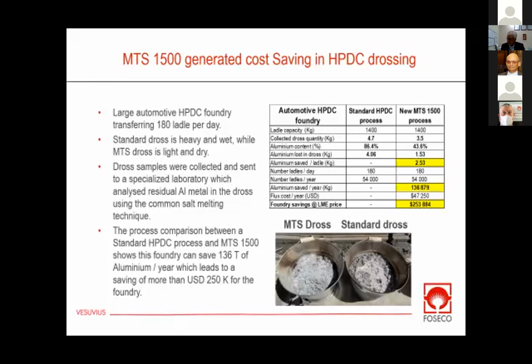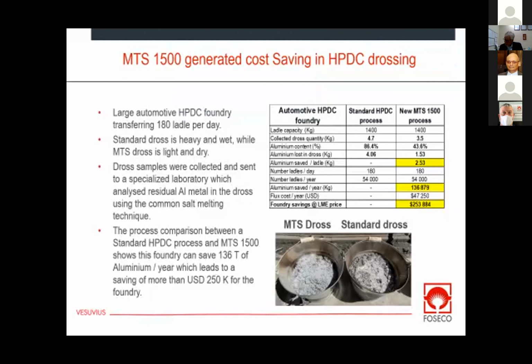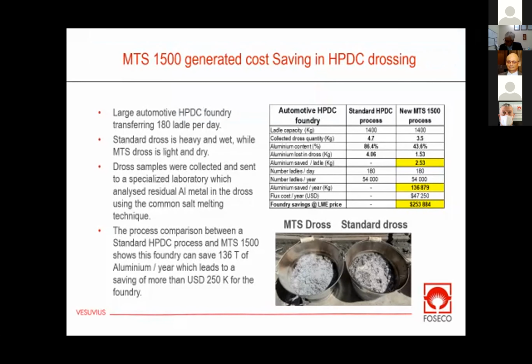We looked at their standard process, and quality-wise, they were very happy. They didn't have any special rejects or issues. But when we looked at the dross on top of their ladle, we saw that the quantity of dross they're generating during melting and processing is extremely large. As you can see in the picture below, we invested in a number of steel buckets, which we used to collect the dross from many ladles being processed in that plant.